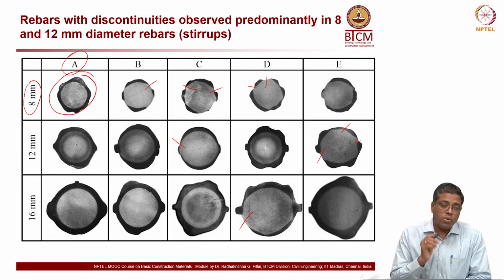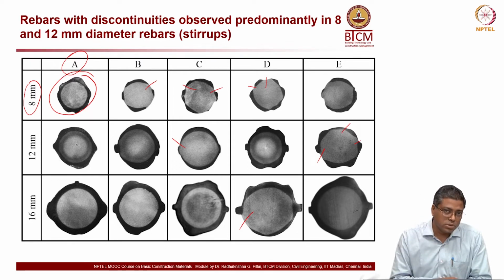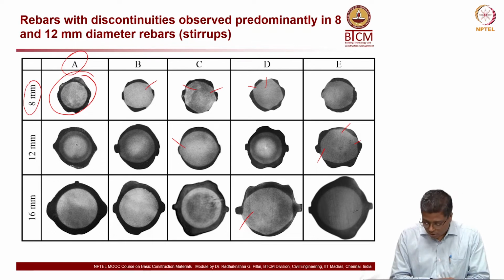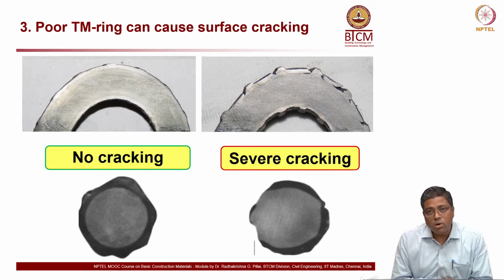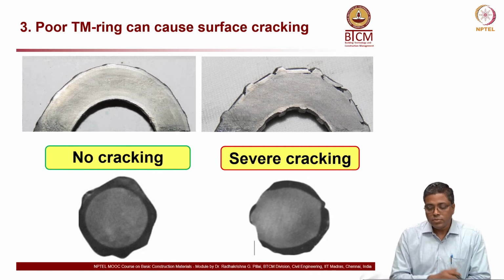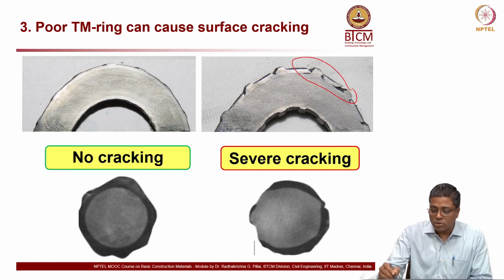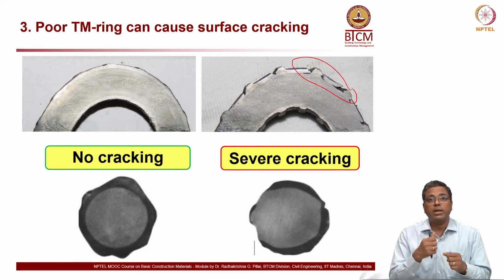What you should do is test the bar with the same diameter which we are using, not a different diameter. Okay, the ring test should be done on the same diameter rebar, and you should look for the proper ring. If you don't have a proper ring, you will have a lot of cracks like this when you bend the bar.